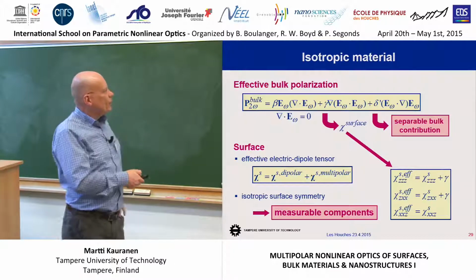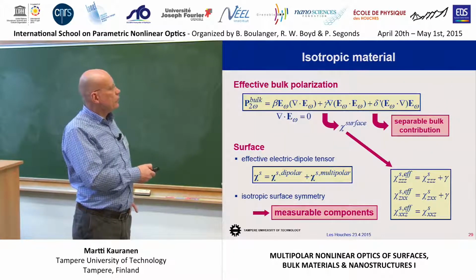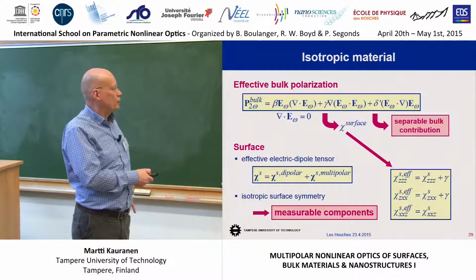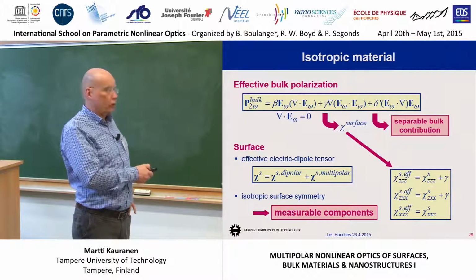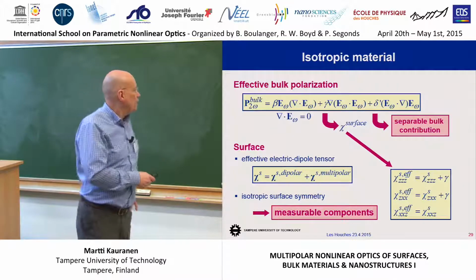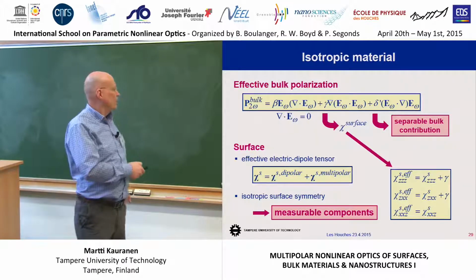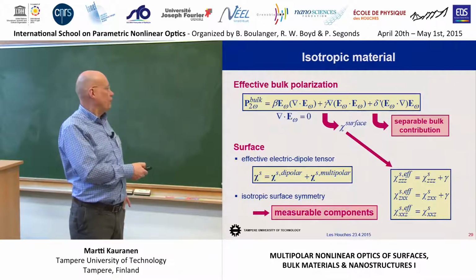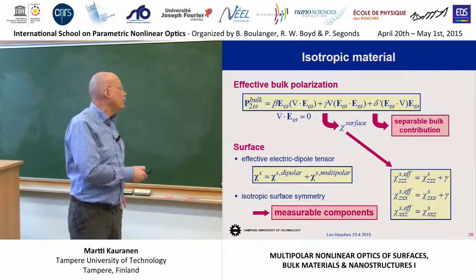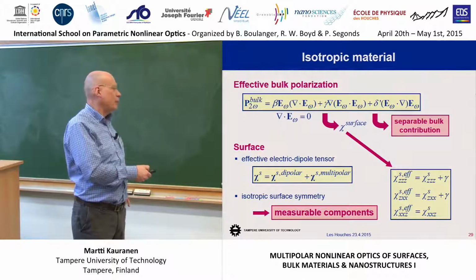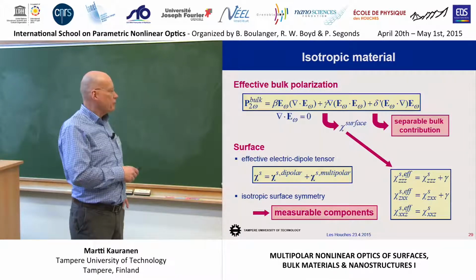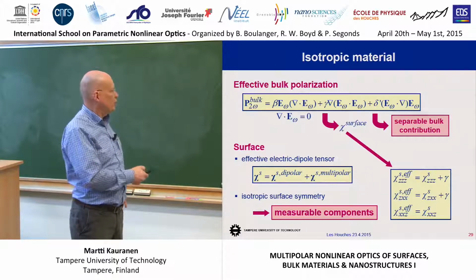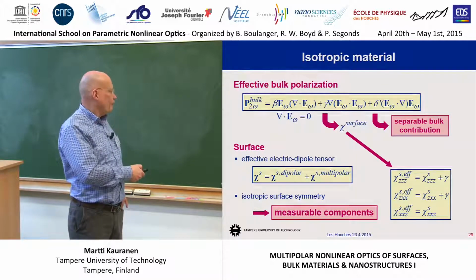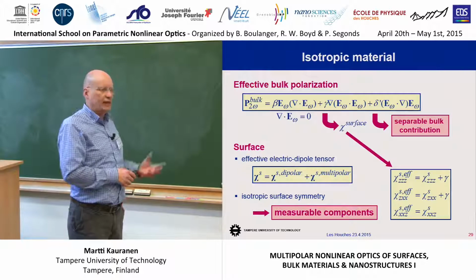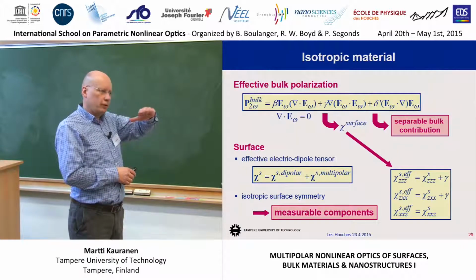And finally, this delta prime is the so-called separable bulk contribution. This is something you could try to measure in an experiment. And then furthermore, at the surface, you have this effective electric dipole tensor, which could have contributions from the dipole interactions and some higher multipole interactions. But in some sense, we are going to assume that it fulfills the symmetry rules of the electric dipole tensor for a surface symmetry.